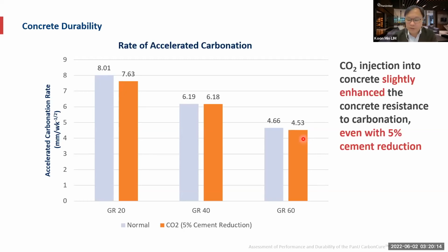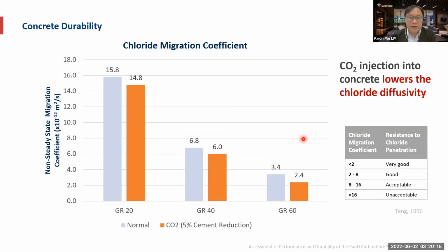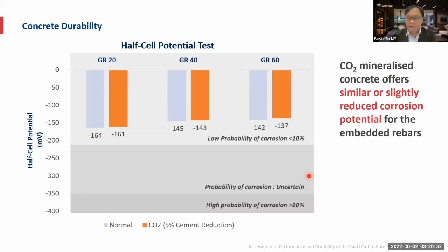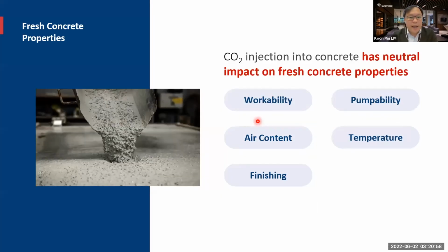in terms of carbonation resistance. And at the same time, the chloride migration coefficient also shows resistance to chloride penetration for CO2 mineralized concrete. It thus has a better performance in this area. And even so, for the half cell potential test that you've seen here, both normal concrete and CO2 mineralized concrete lie in the range of low probability of corrosion. And these are the few tests of concrete durability that show equal, if not better performance in terms of durability, as well as strength, between normal concrete and CO2 concrete. And together with the fresh concrete properties, the CO2 injection has a neutral impact on the various fresh concrete properties that you see here.